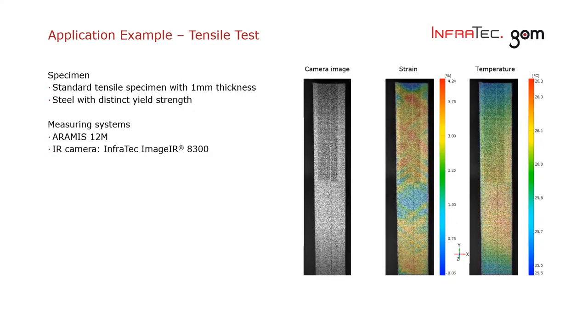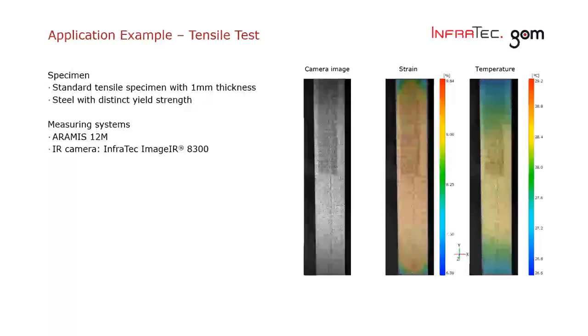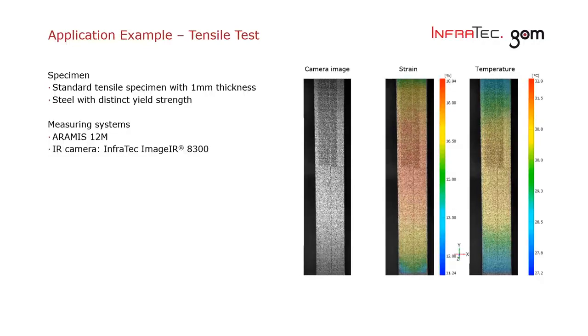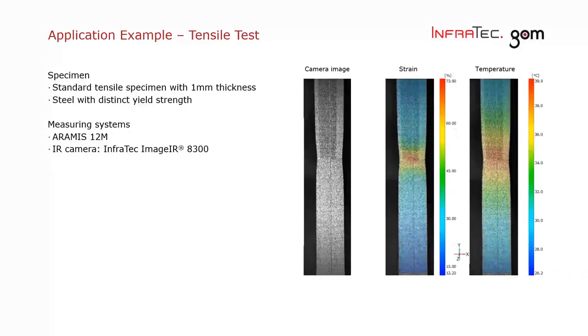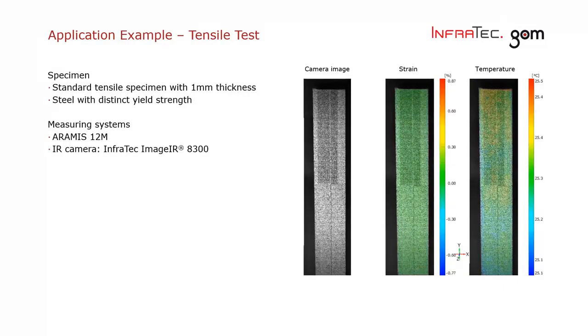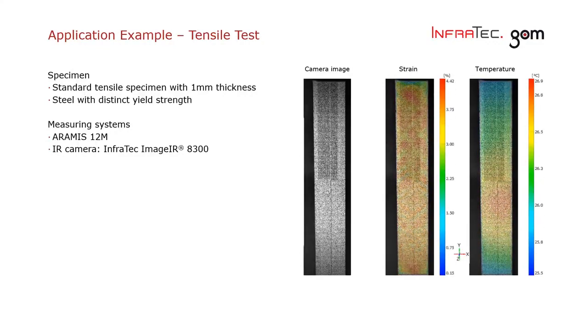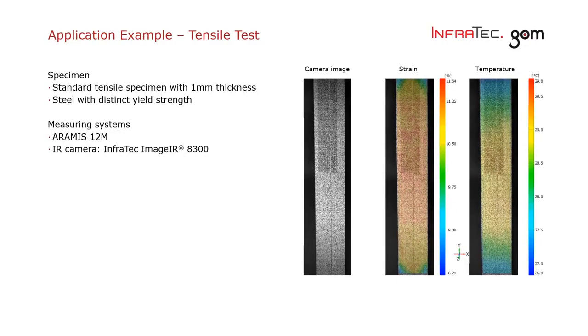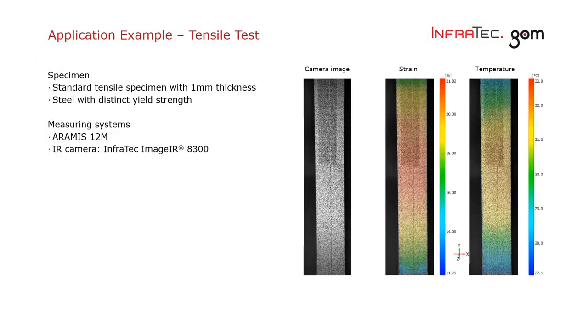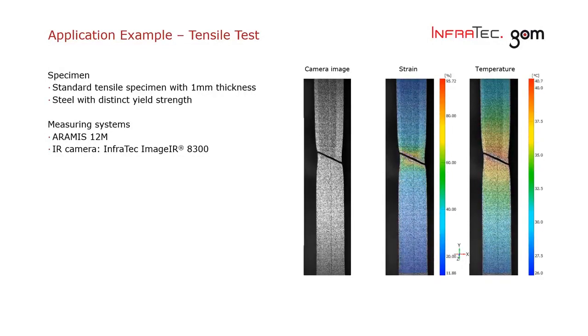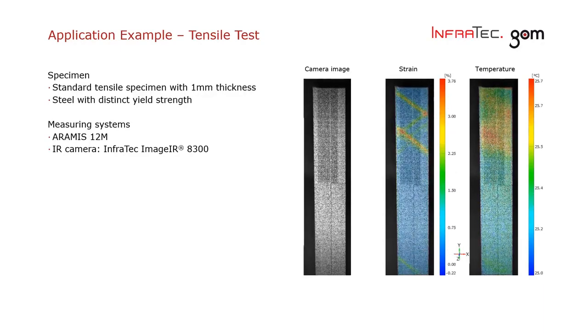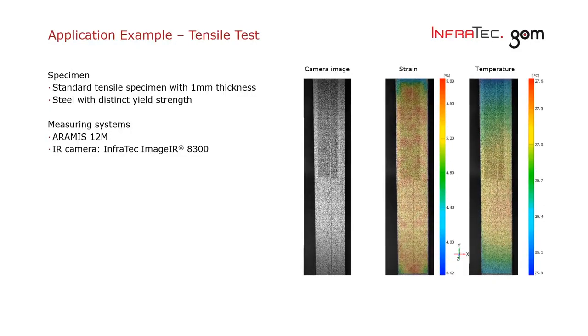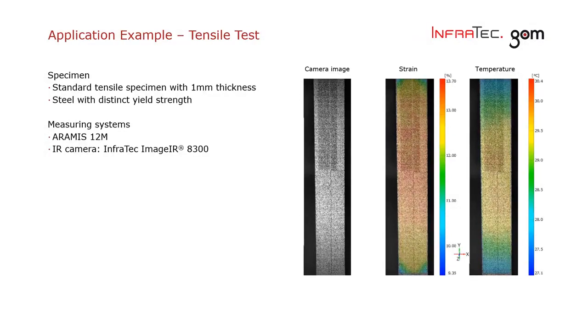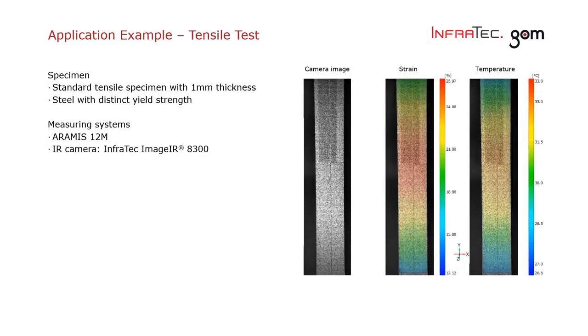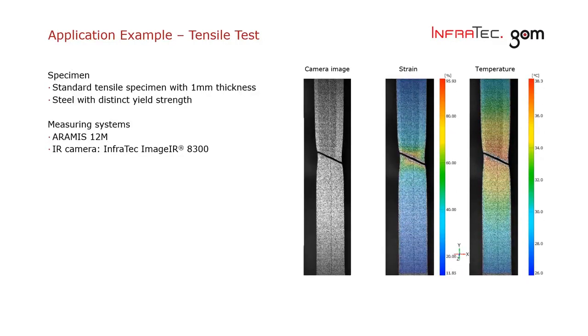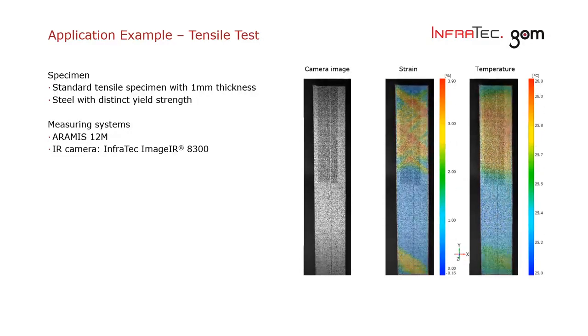Looking on the result representation over here, some of you might have seen Aramis results already. The temperature will be treated in the same kind of way inside the Aramis software later on. This was a standard tensile test that was carried out with a thickness of 1 millimeter steel with distinct yield strengths over here. That's the reason why you see the generation of the Lüders bands in the center image. The Aramis 12M system was used, just that you can get an idea about the resolution, and an InfraTec ImageIR 8300 camera is used to capture the temperature distribution from the specimen surface. The main result that we will see in the end is that the temperature data is available inside the Aramis project and can be directly correlated with the strain or the displacement distributions. And thus it's another measure, another result data set which is available for all evaluations.